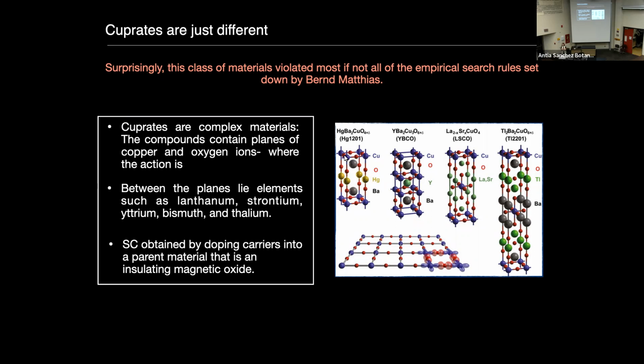This is effectively where the action is in the material, as we're going to see later on. In between those planes, we have spacer ions that can be, as you can see here, mercury, barium, yttrium, lanthanum, strontium, and a few others. And effectively, the way in which superconductivity comes about is by doping carriers into those spacer planes, and you always dope into a parent material that is an insulating magnetic oxide. So again, stay away from oxygen, stay away from magnetism, stay away from insulators, really doesn't work here.